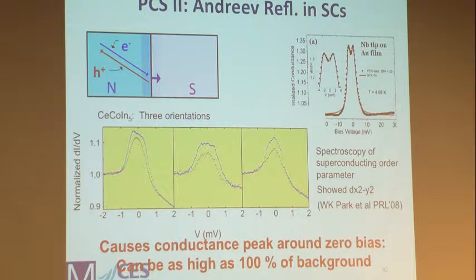And this can be a big effect because Andreev reflection can be as much as 100% reflected. So this could be a big effect, but so that's understood. So we started doing this stuff, and this is just an example in cerium cobalt indium-5, a nice, cute little heavy fermion superconductor, and we notice this anisotropy here. Now, I won't have time to go into this, but Anderson's theorem said you can't have this anisotropy. And I was torn up by some very famous people, like, what's wrong with you? Junctions are bad. And then we finally figured out the problem.